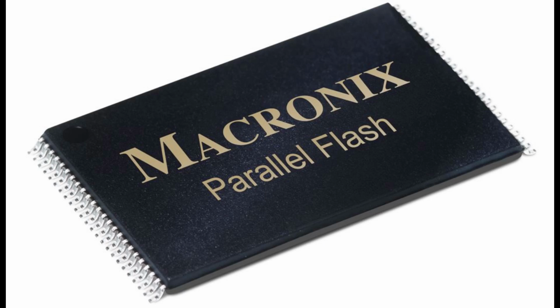Degradation or wear, and the limited endurance of floating gate flash memory, occurs due to the extremely high electric field, 10 million volts per centimeter, experienced by the oxide.